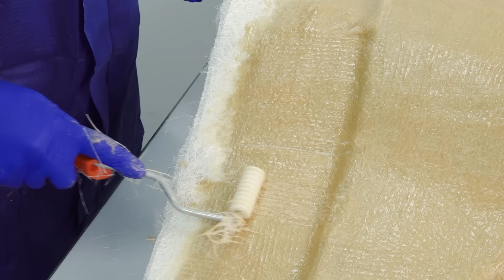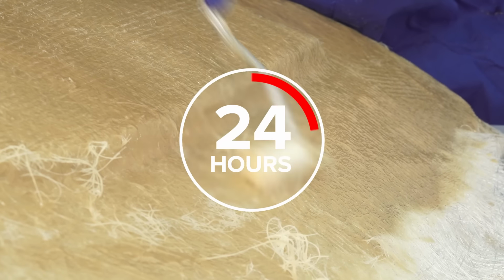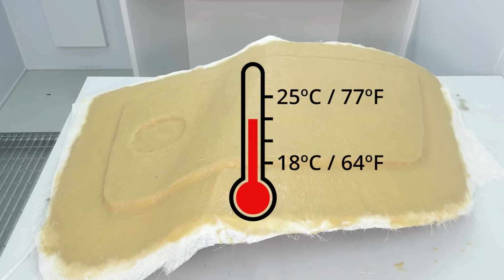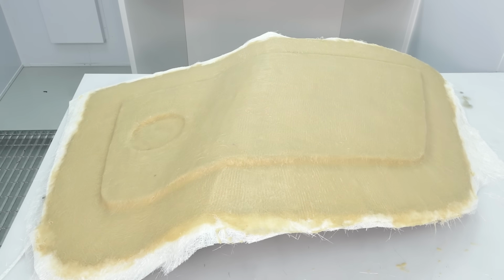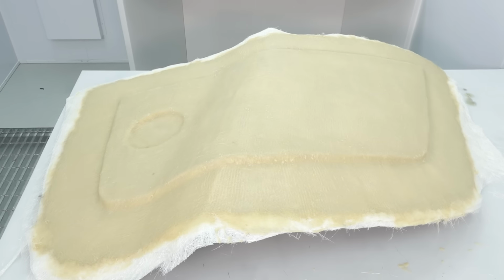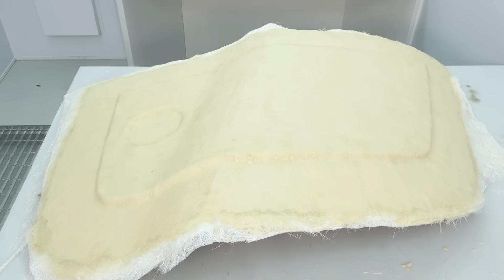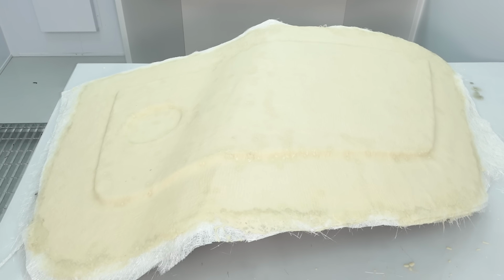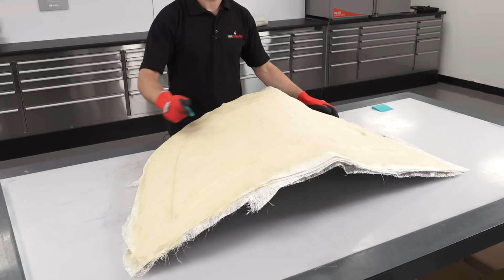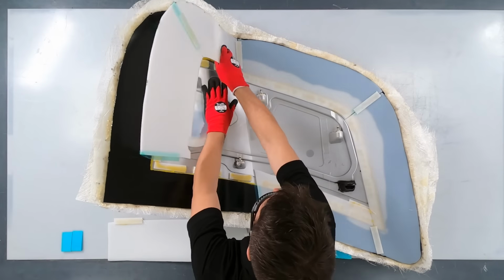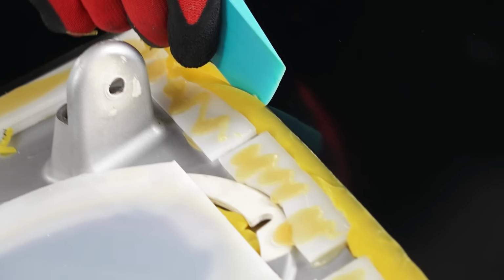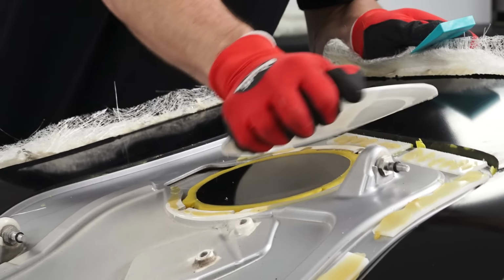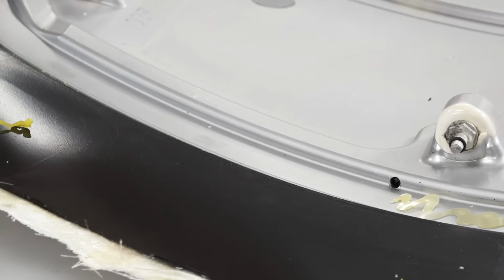Once you're happy that all 4 plies are properly wetted out and consolidated, the mould should be left for 24 hours to cure. Do make sure that during this time you maintain a stable temperature of between 18 and 25 degrees C. As the resin cures, you will notice that the resin will change to a much lighter shade of colour as it peaks on its exotherm and reaches that full cure. We're now 24 hours later and we have a cured mould. The temporary barriers can now be peeled away and the pattern part removed. If the pattern surface was properly prepared and compatible, it should pop out with very little effort.